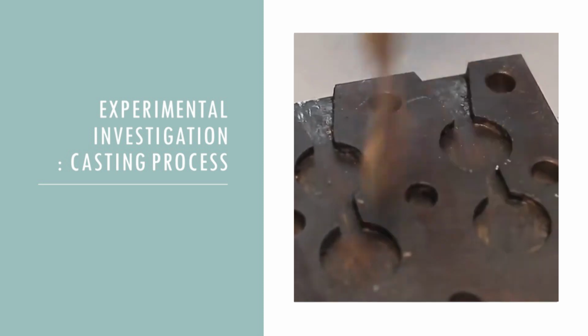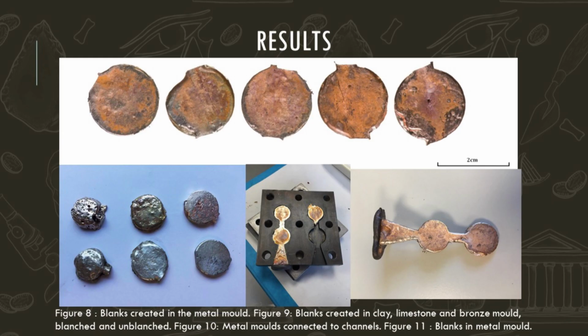So moving on to the results. Although capable of producing blanks, the clay mould presented a range of issues. At the drying stage, the two sides of the mould contracted, making it difficult to achieve a close-fitting connection. If both sides of the close-connected mould had not been completely flat, then flashing will occur and the molten metal seeps out. When the molten metal came into contact with the mould, they often fractured.